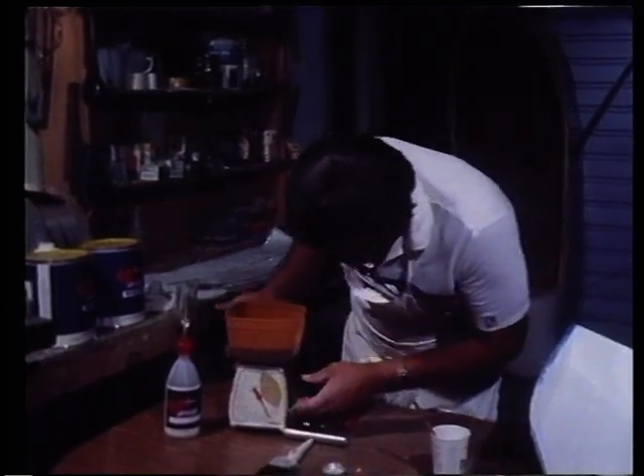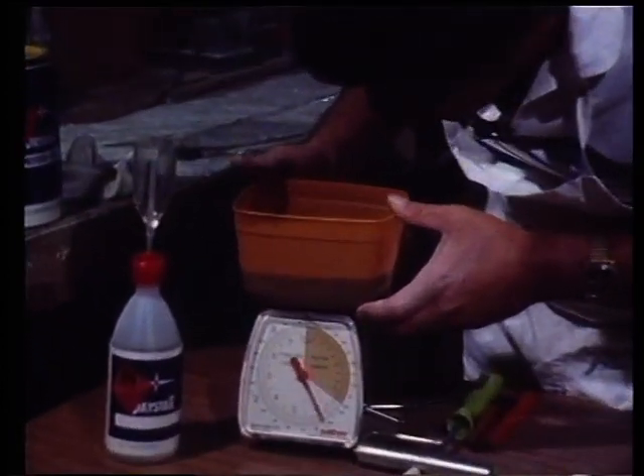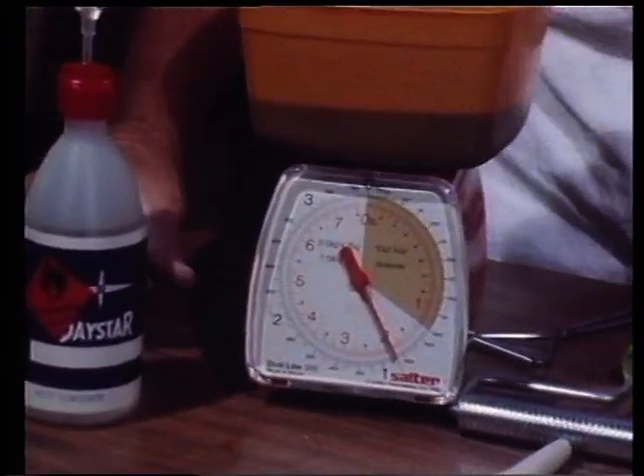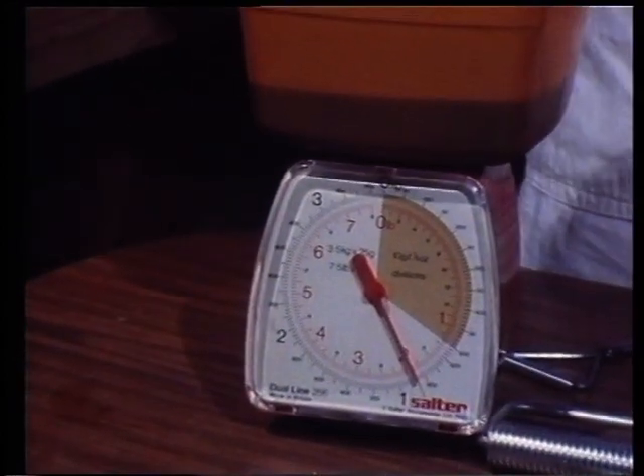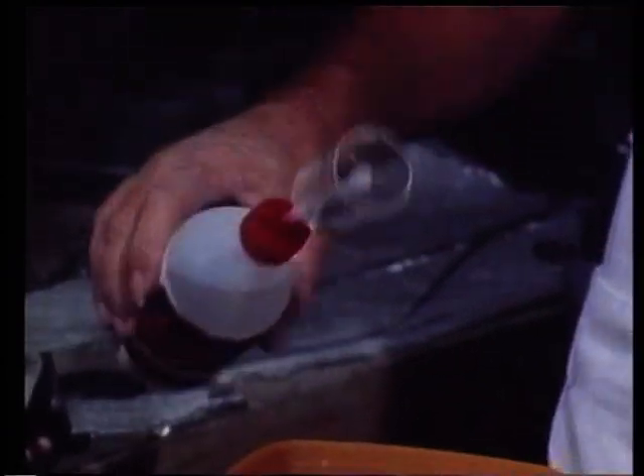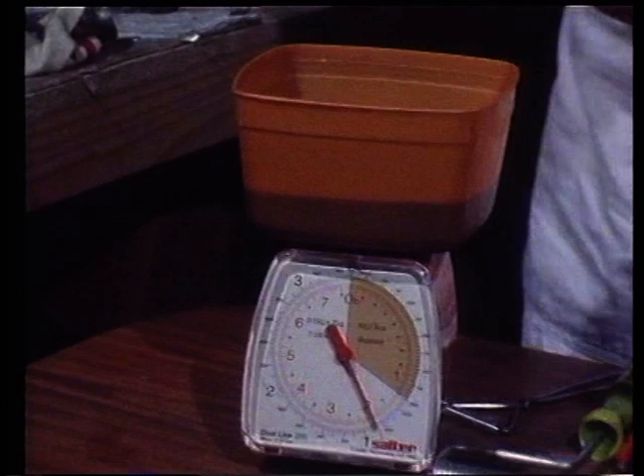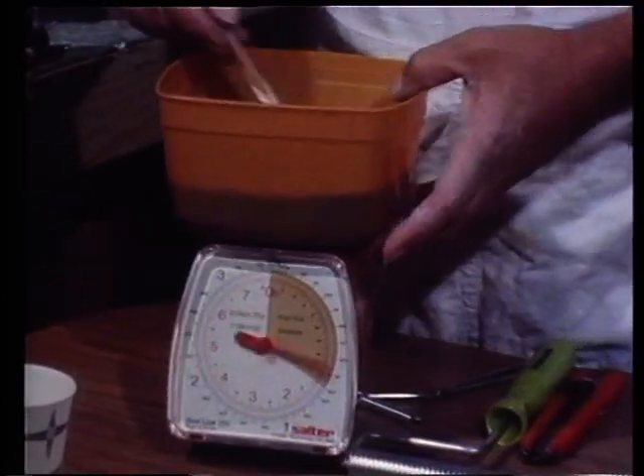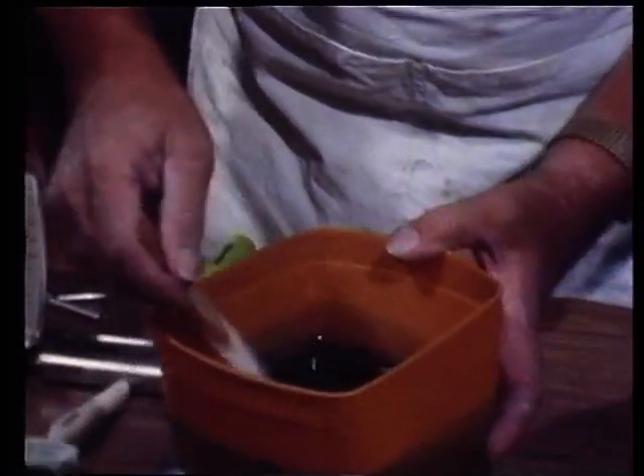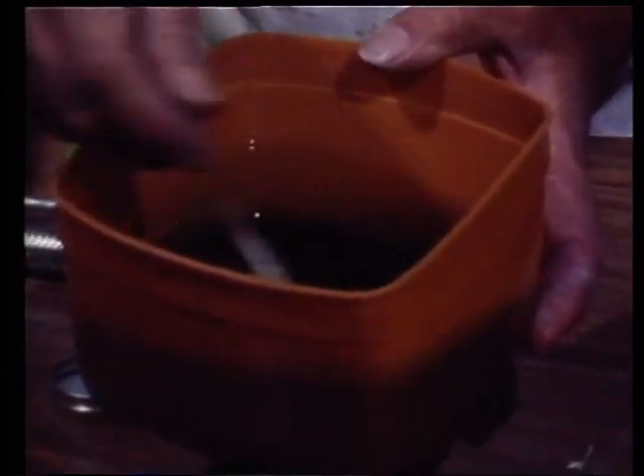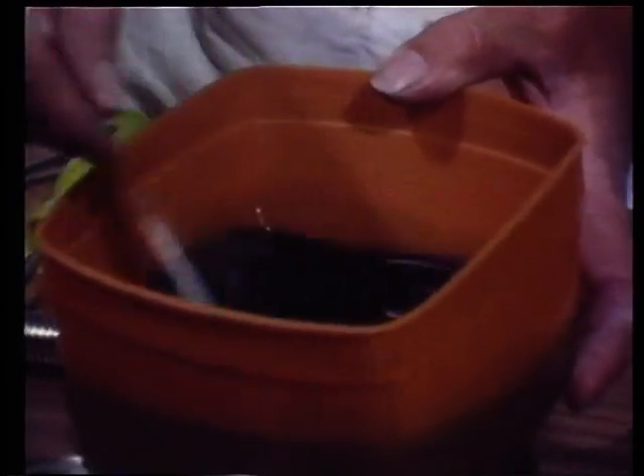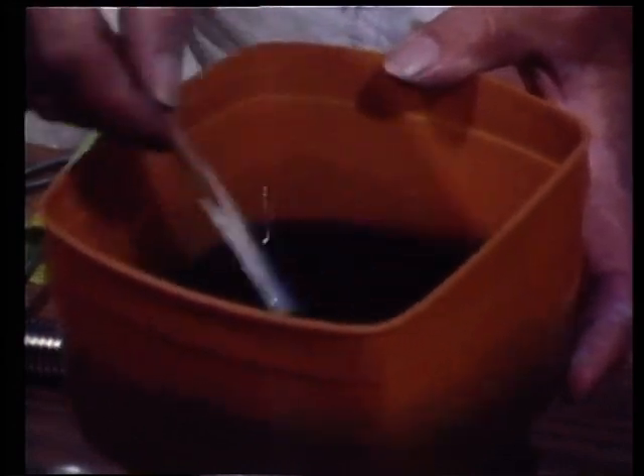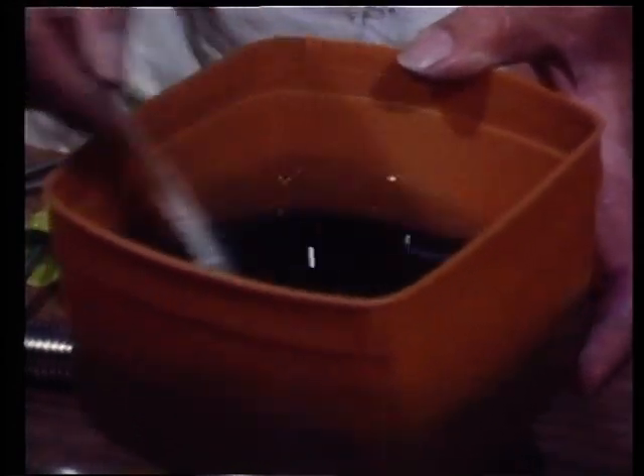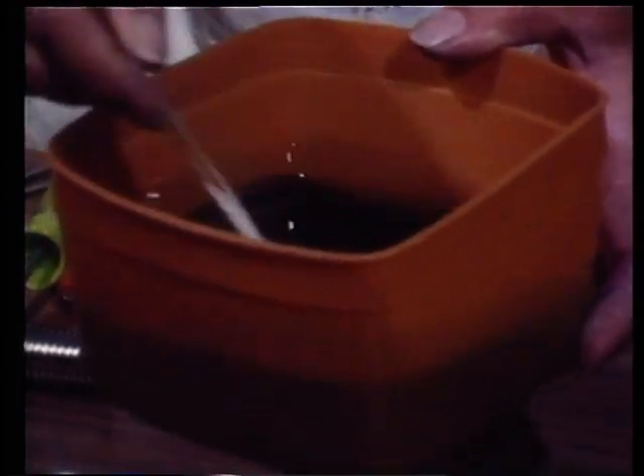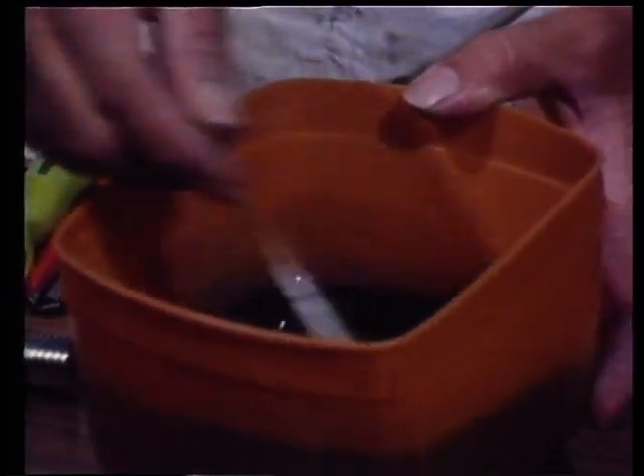Now I'll just have a look at how much we have there. We have exactly a kilo, which is not a bad guess. So I put 10 mils into that, which is there, pour it into the resin, and as we saw with the gel coat, it's essential that it be thoroughly stirred and distributed through the resin. Now, I'll see if I can show you the resin there. You can see that it is a blue colour. That resin is designed so that the peroxide in the catalyst bleaches that blue dye out and gives you an indication as to whether you have catalyst in the resin or not.